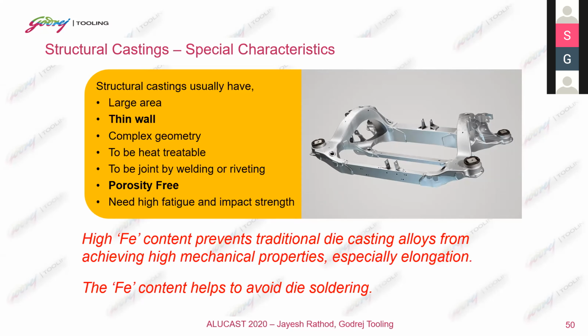But when we look at weldability, it requires a porosity-free casting, because even pinhole porosity will not be allowed here. And with lower Fe content, it will be tough to handle during filling and ejection stages, as mentioned here, it is prone to die soldering, and there the whole thing will start creating problems for us, because we can see a lot of warpage, or the casting may not be able to come out of the dies smoothly and easily.